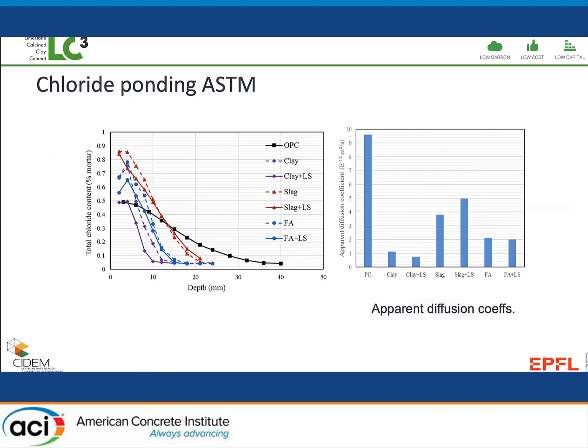This is the one with slag, which is quite a lot better. This is the one with fly ash, which is better again, but the best is the calcined clay and the calcined clay with limestone. And although Yuvraj talked this morning about tortuosity, I'd like to emphasize that it's not really a geometric effect of tortuosity. Our research has really shown that it's much more a direct interaction of the chloride ions with the CSH product.